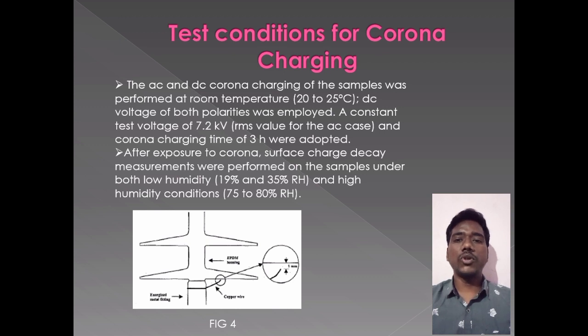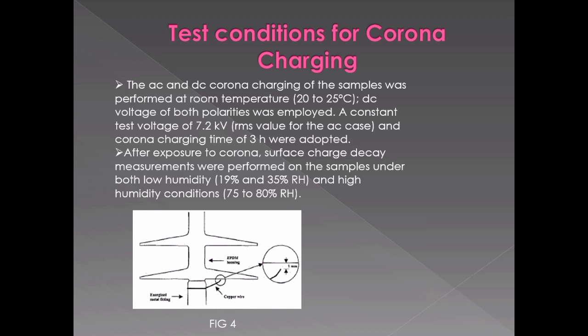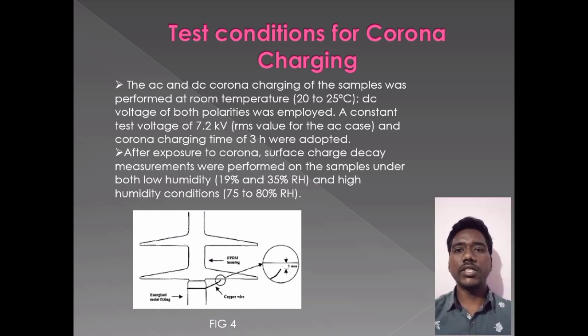As an initial approach to comparative estimation of the degree of influence of corona-related processes on insulators operating under actual service conditions, an additional test setup was arranged. This consisted in exposing the EPDM housing of an actual 15 kV class non-ceramic suspension insulator to impinging corona, and characterizing the PD and frequency with application of both AC and DC high voltage.